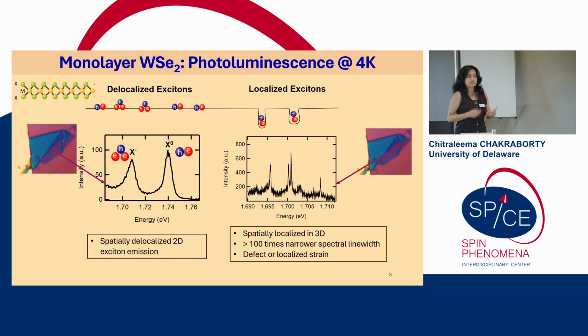The origin of these quantum emitters is a combination of the presence of defects and strain in the material, which helps the exciton to funnel right at the position of the defect. In that way you can spatially isolate a single exciton in this material and improve the spatial resolution of whatever it is that you are measuring with these localized excitons. So this is one feature that we leverage to study these magnetic heterostructures.